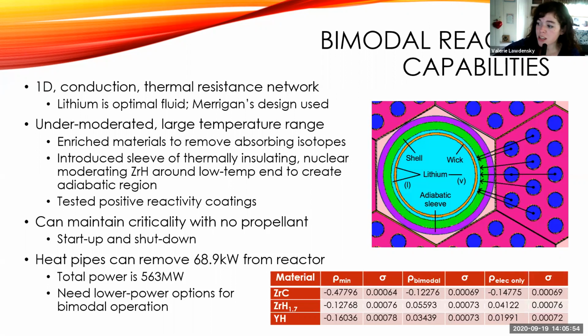The two configurations we tested were a bimodal, in which we just assessed them both, and an electric only, to see what would happen if there wasn't the hydrogen, which is also a very good moderator, in the channels. And it performed, it succeeded. Unfortunately, because of their very, very low melting temperature, you can't just put them along the entire length of the heat pipe. What we would have to do is put them only at the low temperature end of the heat pipe and reactor, because it ranges from 100 Kelvin to 2500 Kelvin.